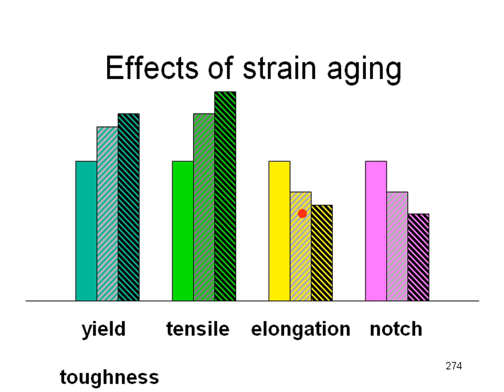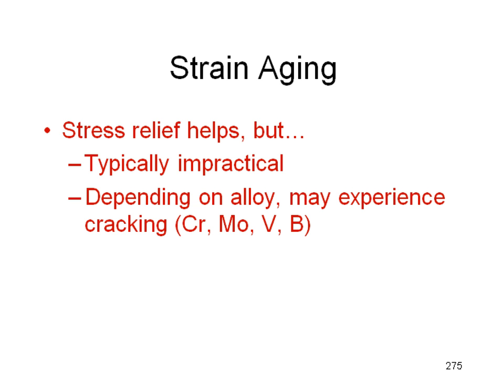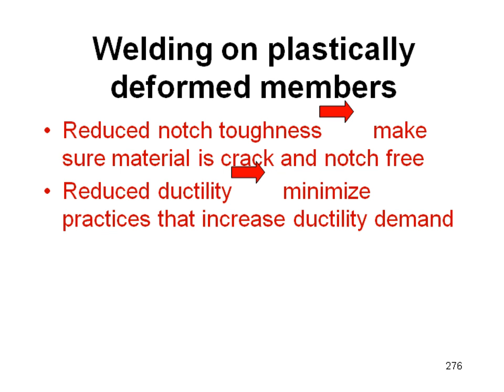Now, the amount of strain aging we experience depends on the chemistry of the material. Stress relief can help, but that's impractical. So what I'd like to suggest is that when we start welding on materials that have been plastically deformed, we need to acknowledge that we have reduced notch toughness, and we need to make sure the material starts out notch and crack free. So when we have these cold worked areas, let's get those areas ground real nice and smooth. Because we have reduced ductility, we want to minimize the practices that increase the demand for ductility. And of course, we went through that under the provisions on welding on highly restrained material.